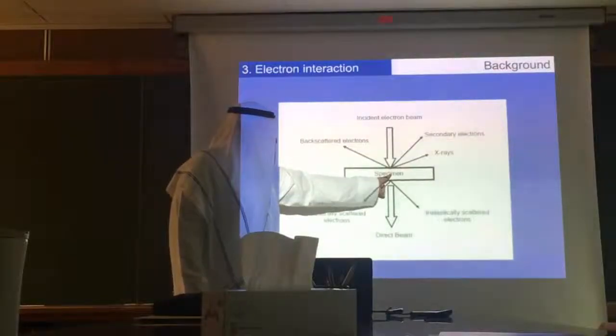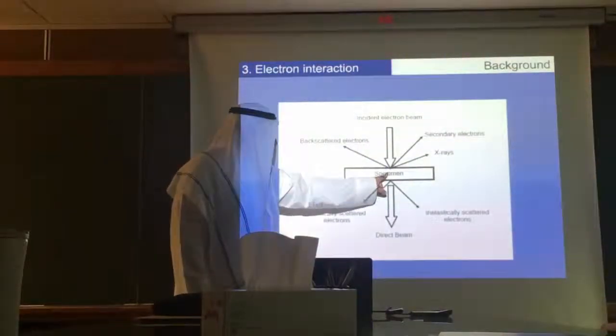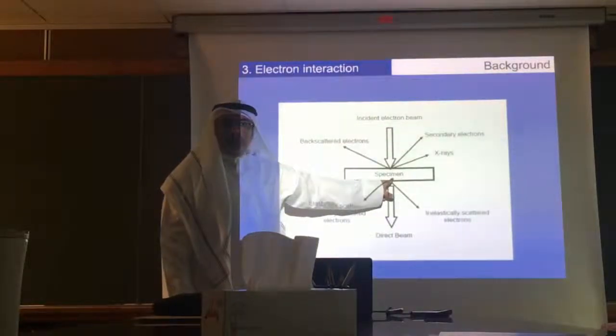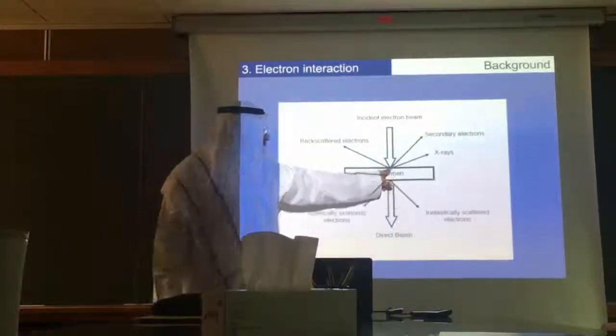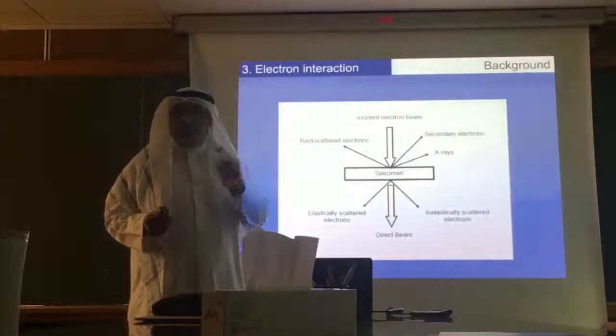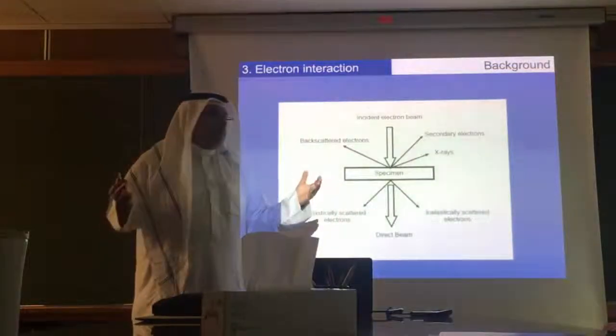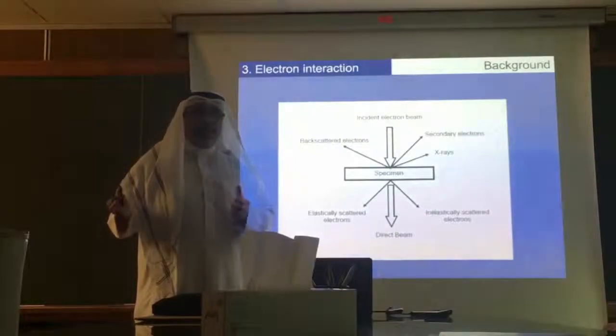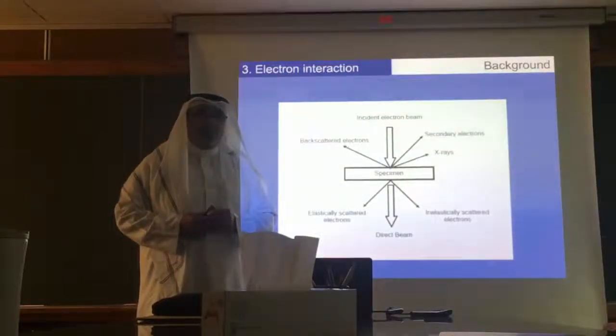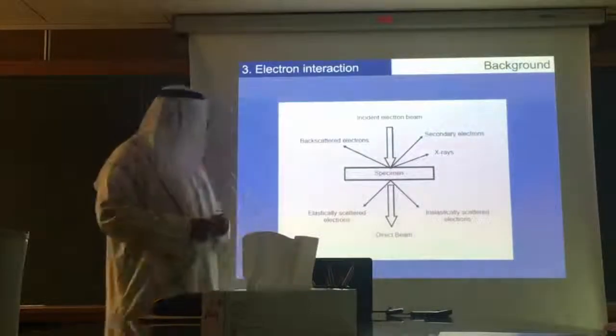And there is a very interesting signal from the sample. When you bombard your sample with electrons and eject an electron, there will be, let's say, a hole in this place. Another electron comes down from the excited state to the lower state, and because the electron comes down, it will emit X-ray. It will emit light, but the light is actually in the X-ray range. And they found out each element will emit different X-rays, so I can actually know what element this is. If I have carbon, I will know how much carbon I have in my sample. This technology is called EDS or EDX, which stands for energy dispersive spectroscopy, or X-ray. Very interesting to know the composition of the surface and near surface.